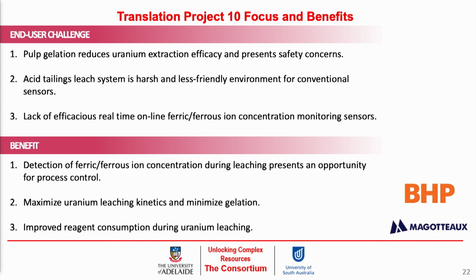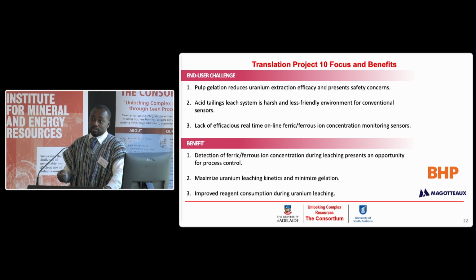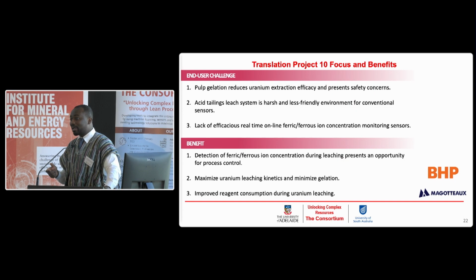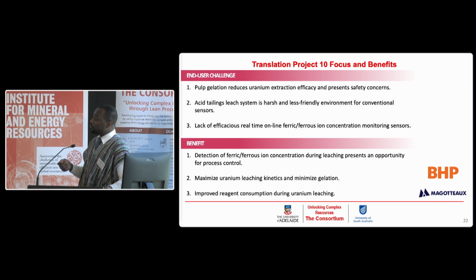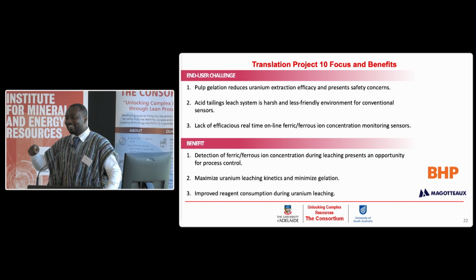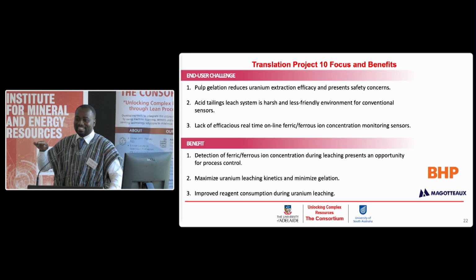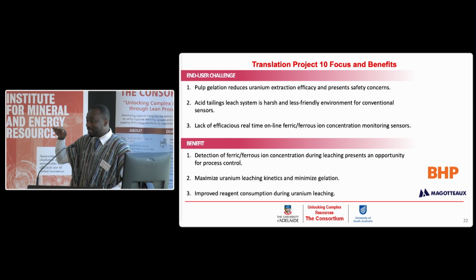This translation project is to address key challenges such as pulp gelation, and this is very important because in uranium leaching you need ferric ion to help oxidize the uraninite, the uranium mineral, in the leaching process. If you don't have enough ferric ion, what is usually used to monitor that is the redox potential, but the most critical parameter is the ferric ion. So on plants, you just end up dosing a lot of oxidants to move up the redox potential to a particular target value.